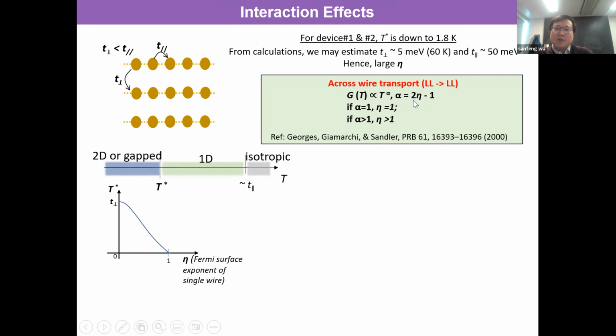Do more careful calculations. But we have to also be careful how to really apply this to the system that we're talking about here. The theory would suggest alpha equals 2 eta minus 1, considering the device geometry, that the wires are parallel to each other. So if you use this formula, it's saying that if your experimental data where T to the alpha is about 1, then you estimate eta in the wire effectively is also 1. So we're actually very close to the transition. We are in a very good range, saying that interaction could be strong enough to stabilize a 2D Luttinger liquid.